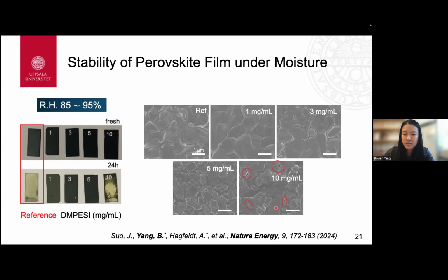These cracks could easily provide degradation pathways for moisture from the external atmosphere to penetrate into the perovskite bulk, especially under high relative humidity conditions. This would lead to an accelerated degradation process. That is why we see severe spot-like degradation centers in these films at very high relative humidities.